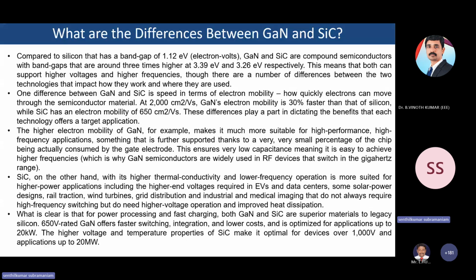So one difference between GaN and SiC is speed in terms of electron mobility, how quickly electrons can move through the semiconductor material. At 2000 centimeters squared per volt-second, GaN electron mobility is about 30% faster than that of silicon, while SiC has an electron mobility of 650 centimeters squared per volt-second. So these differences play a part in dictating the benefits that each technology offers a target application. The higher electron mobility of GaN, for example, makes it much more suitable for high performance, high frequency applications, something that is further supported thanks to a very, very small percentage of the chip being consumed by the gate electrode.